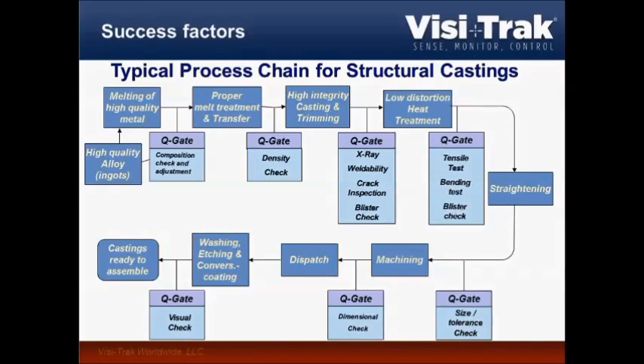So you do your tensile test or bending test. You do a blister check, because heat treatment is also a very good testing method to see how sound your casting quality is. Any bubbles will now have blistered up. Then you might have to do some straightening. Then size tolerance check, dimensional check after machining, and then it usually gets sent out, and any surface coating is typically done right before the parts get assembled.